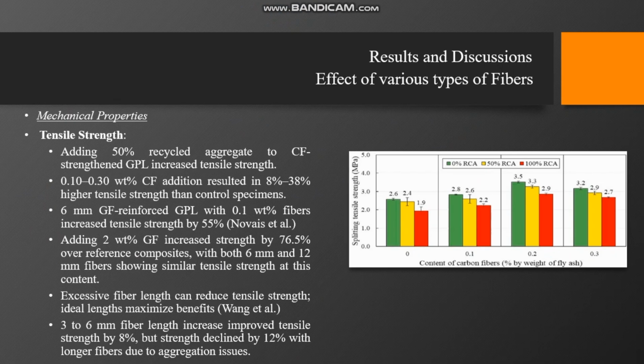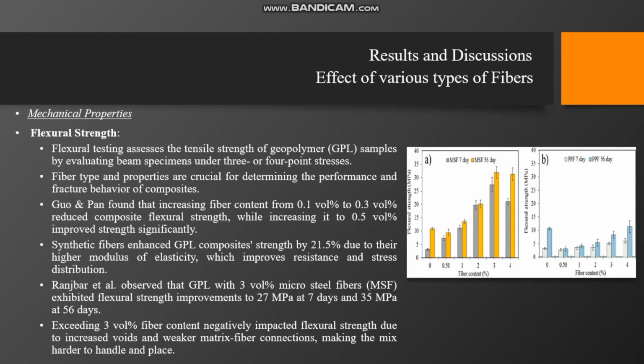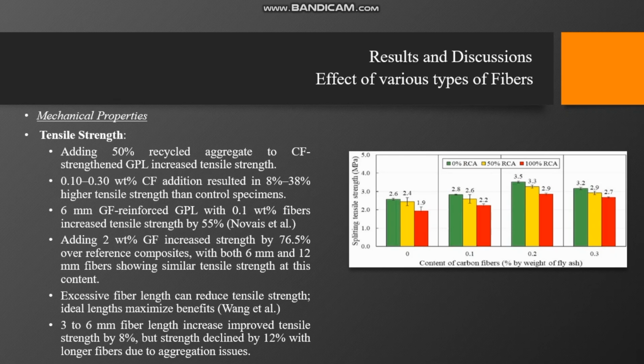Next, we have the tensile strength among the mechanical properties. Adding 50% recycled aggregate to the geopolymer increased tensile strength from 0.10 to 0.30. Weight percentage addition resulted in 8% to 38% higher tensile strength than control specimens. The 6 millimeter reinforced geopolymer with 0.1% weight percent fibers increased the tensile strength by 55%. Excessive fiber length can reduce the tensile strength. Ideal lengths maximize the benefits. That was quoted by Wang et al.